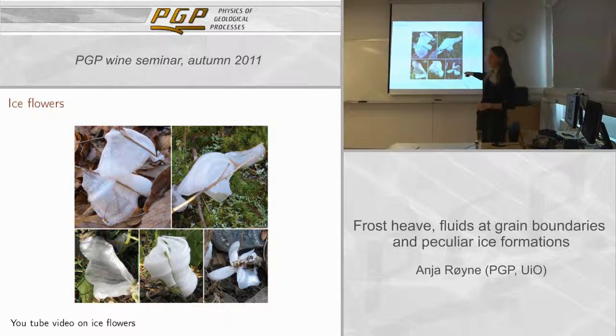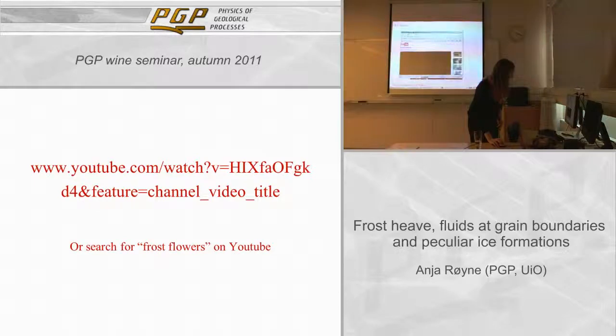It's lots of ice. So all of this water wasn't in the stem to begin with. The stem has been containing water, and then the temperature drops, and then you nucleate ice just on the outside of the porous material. And then water is drawn to where it freezes, and it's just being pushed out, and it's drawing water up from the soil.